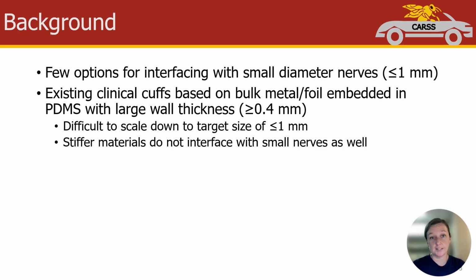The motivation for this nest is the current lack of options for interfacing with nerves less than or equal to 1 millimeter in diameter. Existing clinical cuff electrodes are built from bulk metal or metal foil embedded in thick PDMS, which is difficult to scale down to a sub-millimeter size. Additionally, stiffer bulk metals don't interface well with small, delicate nerves due to their difference in mechanical properties.